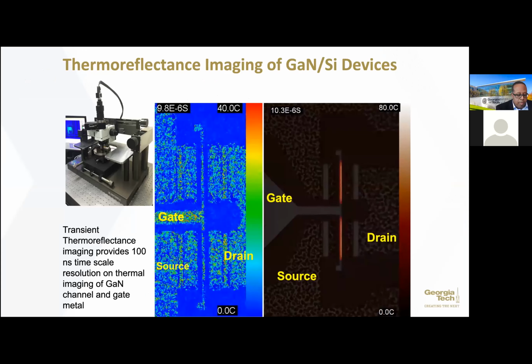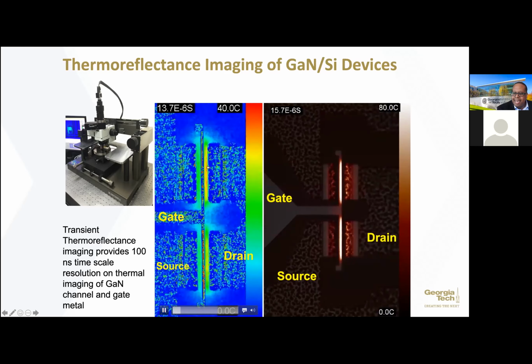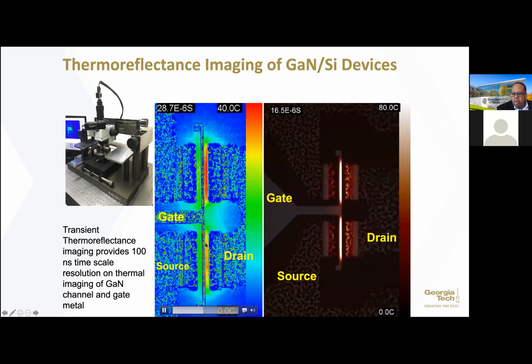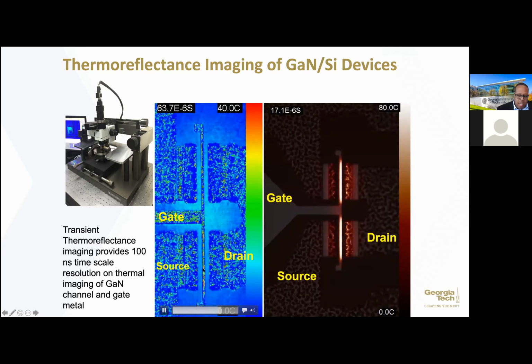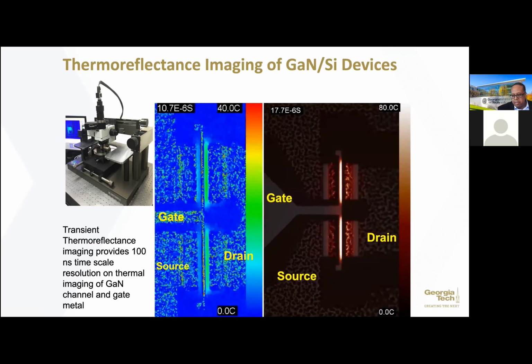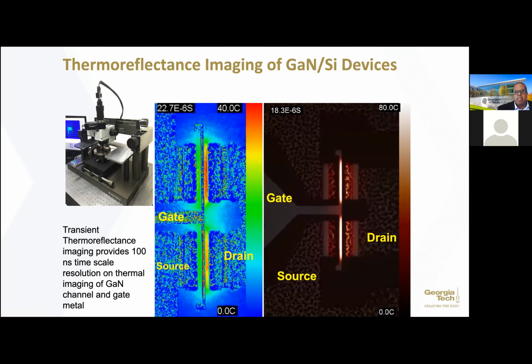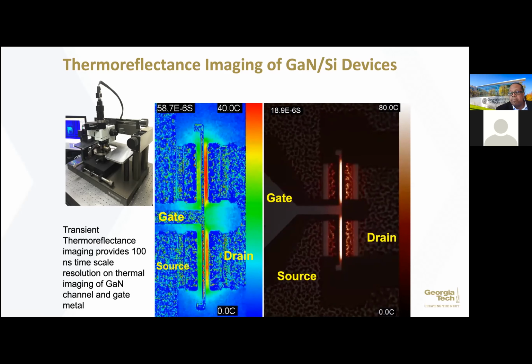Now moving on to thermal reflectance, what we've been able to do here is use transient thermal reflectance. We're actually watching this two-finger HEMT, the gate structure, heat up. You can see this is 100 nanosecond time steps, so we do very, very high speed imaging of the heating of the device. We can also see qualitatively the heating that occurs in the channel. We're going to use this technique to image thermally what happens to the temperature on the gate when I have superlattice structures and when I don't.